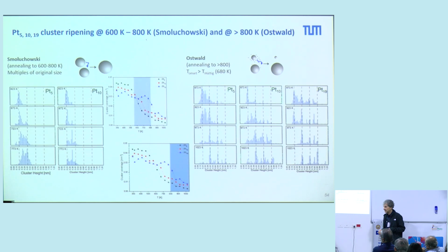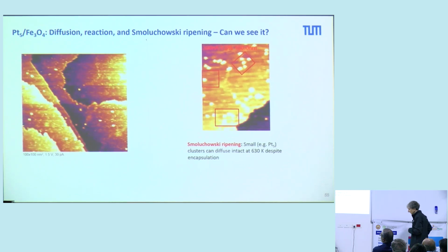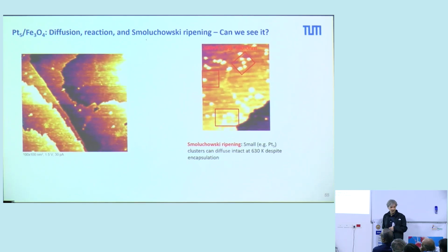Now you have Ostwald ripening. That means you grow larger clusters at the expense of smaller clusters. You see even very small clusters which are disappearing and forming large clusters. So we have a rather good picture of what happens with a cluster on the surface when you are heating up. They are stable. We have a reverse spillover, we have an encapsulation, and then we have the formation of larger clusters. Now the question is, can you observe this in real time?